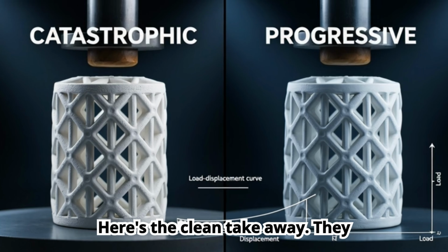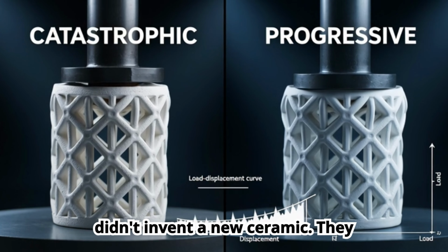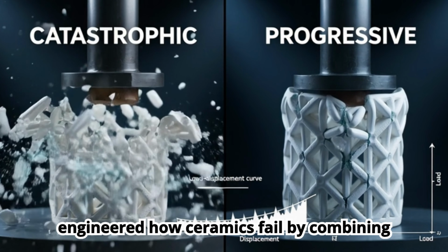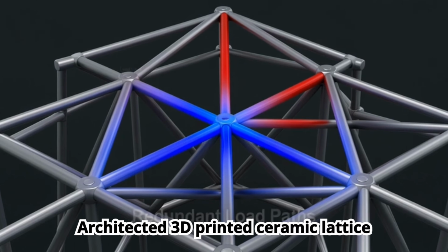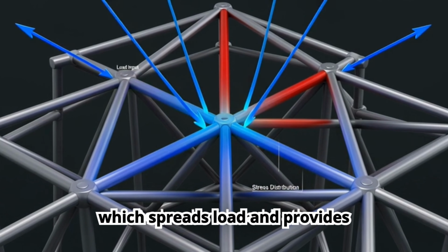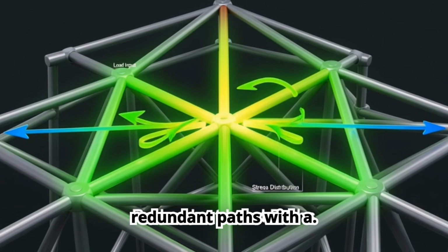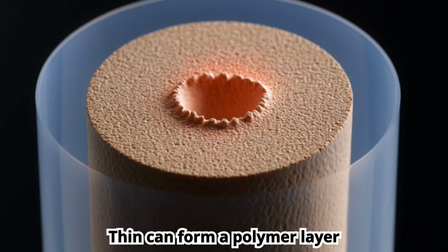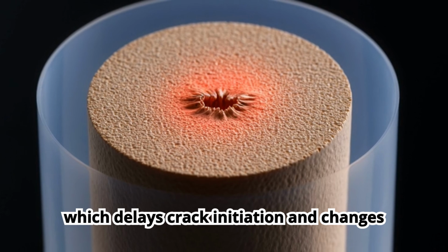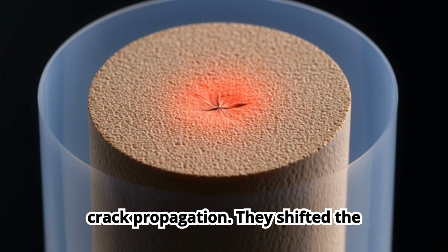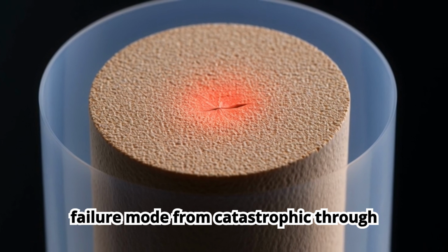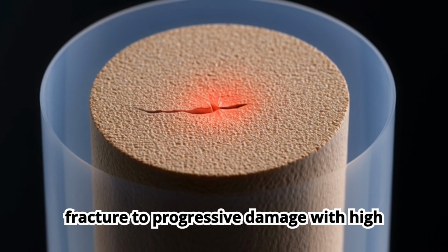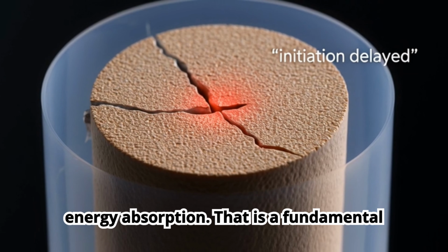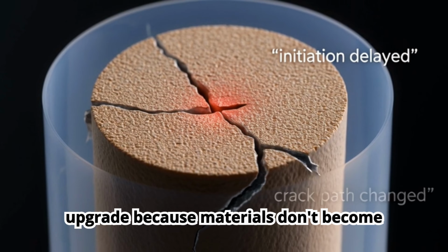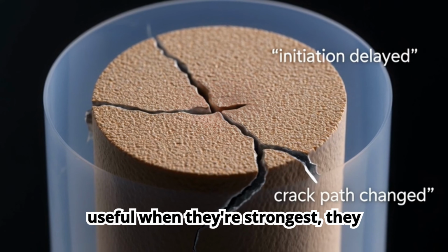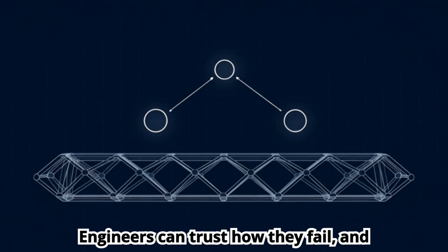Here's the clean takeaway. They didn't invent a new ceramic. They engineered how ceramics fail by combining an architected 3D printed ceramic lattice, which spreads load and provides redundant paths, with a thin conformal polymer layer, which delays crack initiation and changes crack propagation. They shifted the failure mode from catastrophic brittle fracture to progressive damage with high energy absorption. That is a fundamental upgrade, because materials don't become useful when they're strongest. They become useful when engineers can trust how they fail.